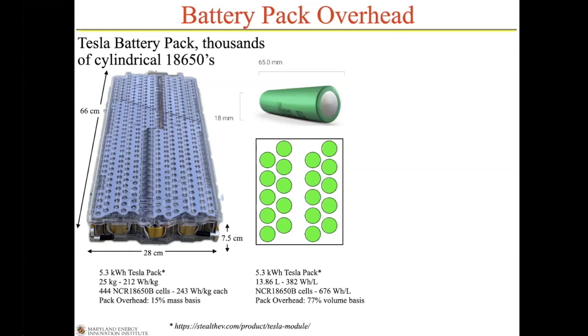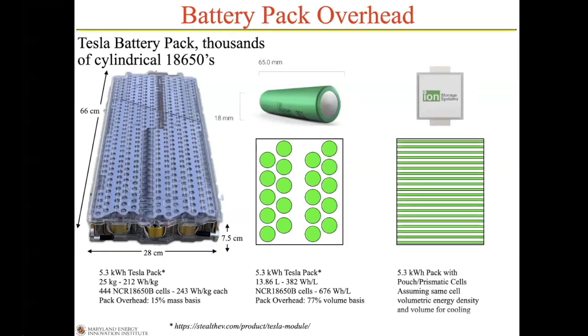And you can see basically based on the way that they're packed in that pack, that basically there's a 77% volume pack overhead. They're taking more volume to enable the cooling than they would have if they were just packed spheres together, okay, or packed cylinders together. So what I'm also going to show you then is now what happens if rather than a cylindrical battery, we had either pouch or prismatic cells, which are these sort of planar configuration. And the cross-sectional area, see to the right of each of those little green rectangles, is the exact same area as the area of the circles to the left.